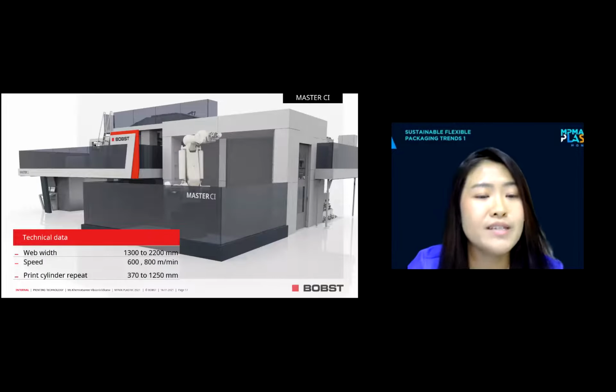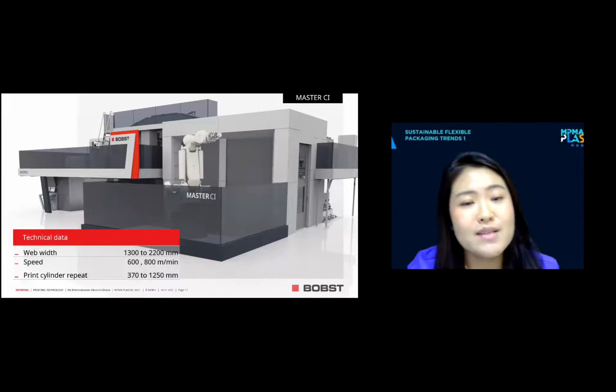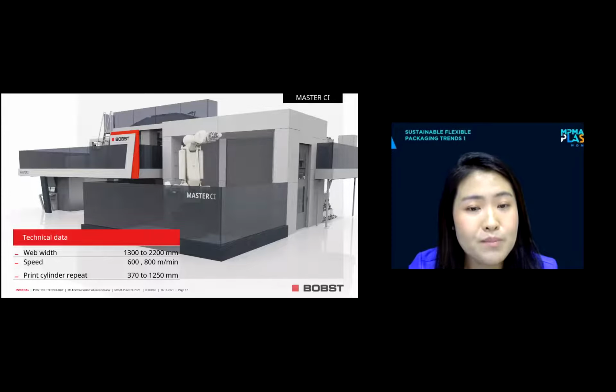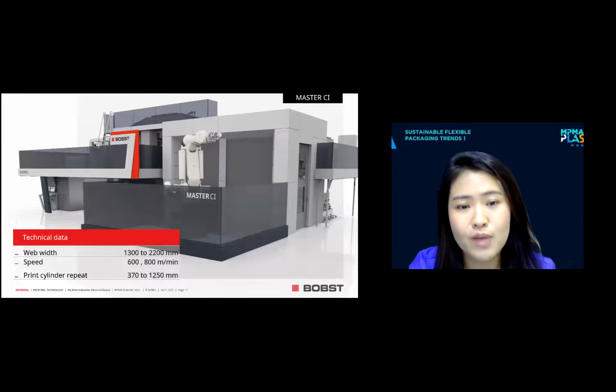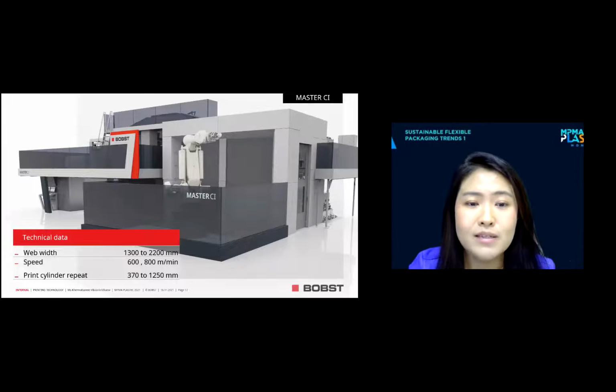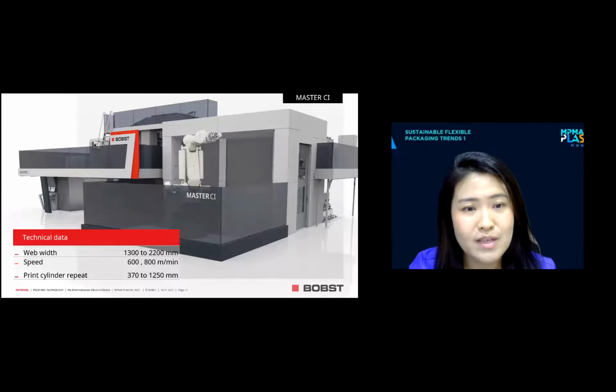So this is our technical data. For the Master CI, we talk about a web width from 1.3 available up to 2.2 meters. The maximum speed is 800 meters per minute, with an option of 600 meters per minute. And the print repeat is available from 370 to 1.25. So I think for flexible packaging, a web width like this is already enough.